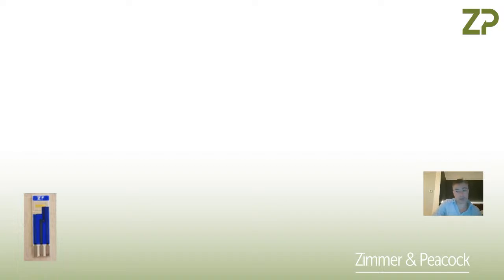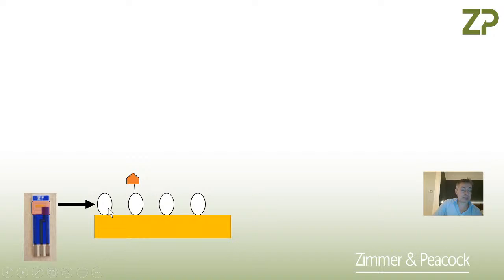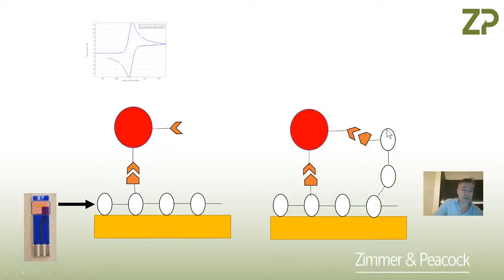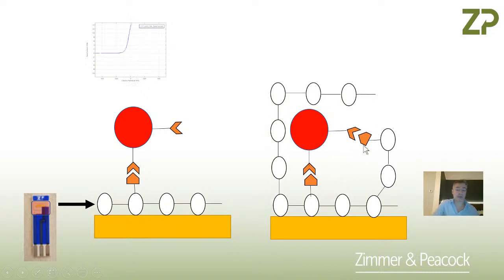Take one of our gold electrodes, add the solution, and we add a ratio of, let's say, neutral monomers and a functionalized monomer. And now we get a specific binding to our template, because our template has on it these lock moieties, which lock with our key moiety here. We do cyclic voltammetry, and we essentially start polymerizing around the template. And we create a pore, now again with functional groups. And if we wash that away, we're in a similar situation to the one I just showed, where we actually have a pore which has the right shape and it has functional groups sticking into it, and that really helps with the specificity.